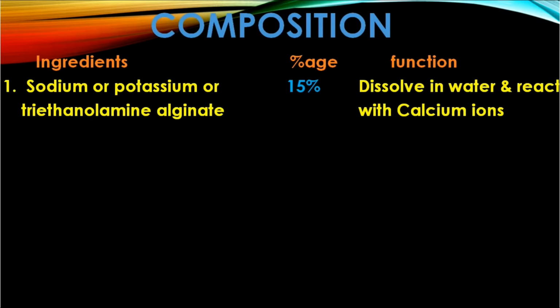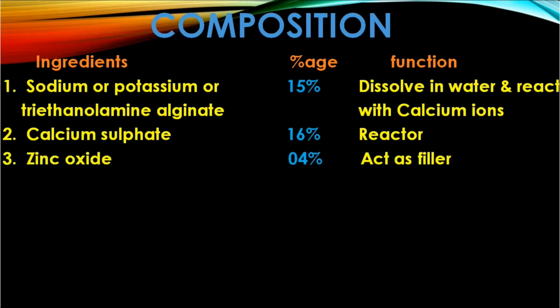Composition: 15% sodium or potassium or triethanolamine alginate, which dissolves in water and reacts with calcium ions. 16% calcium sulfate as reactor. Zinc oxide 4% acts as filler.